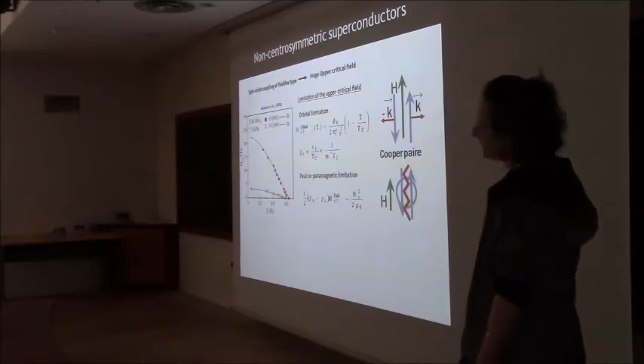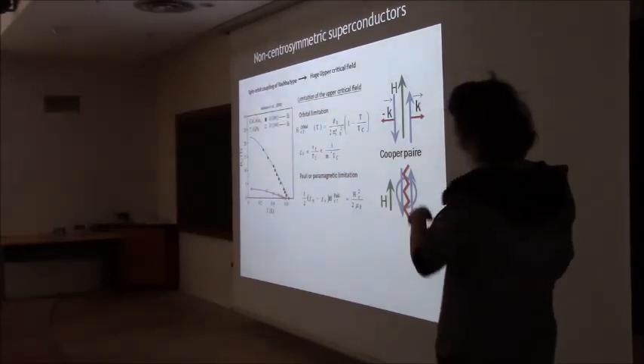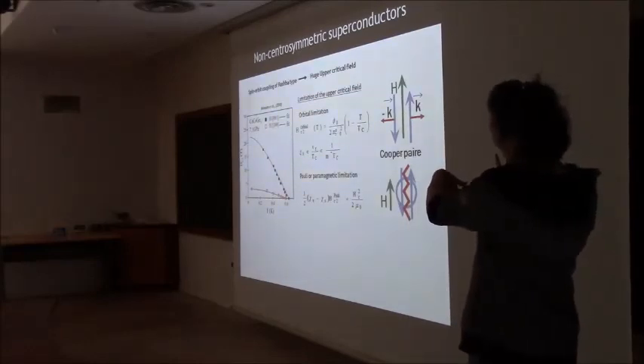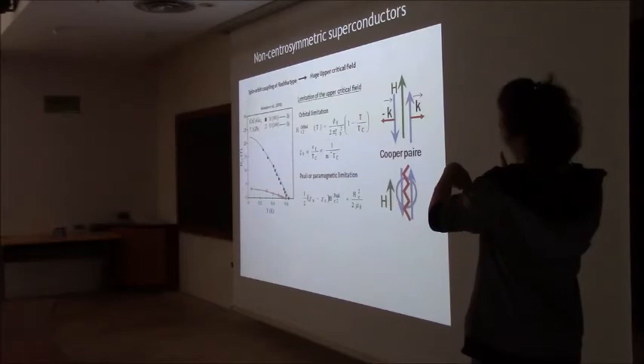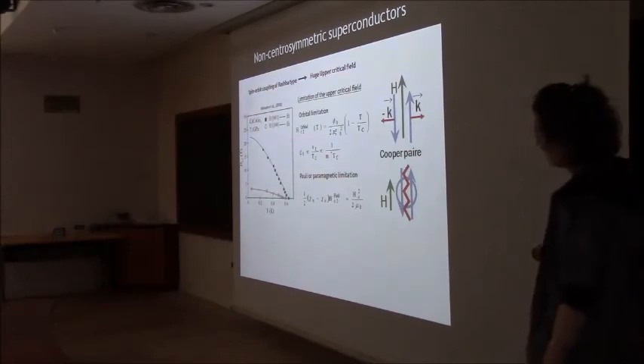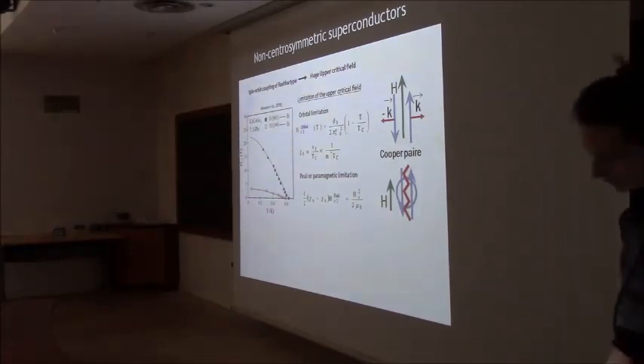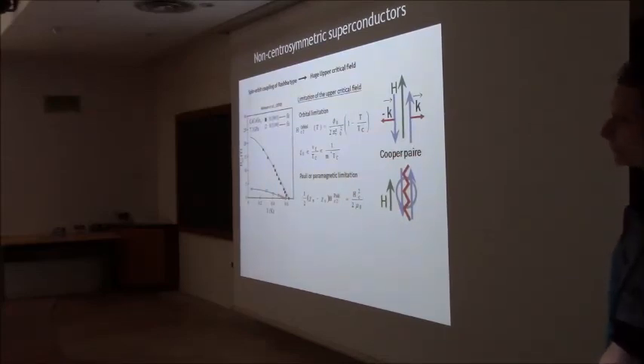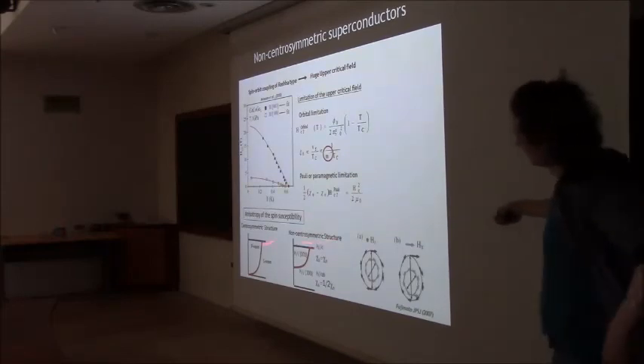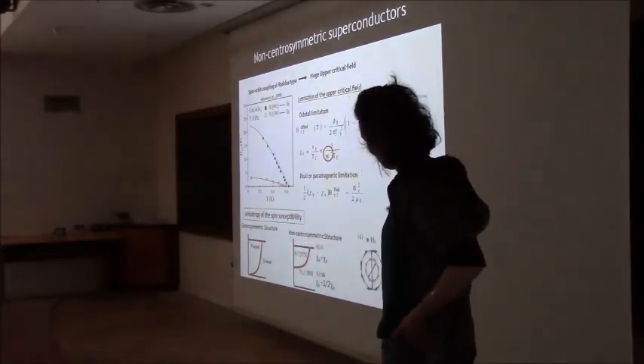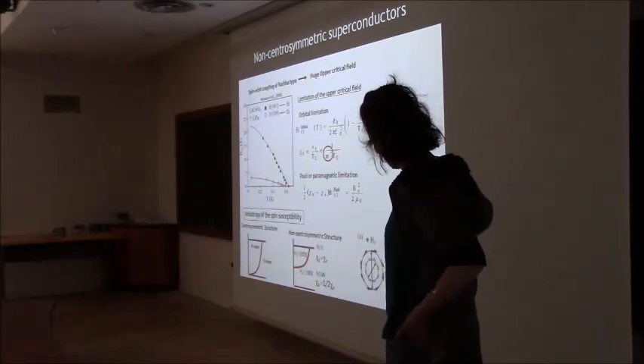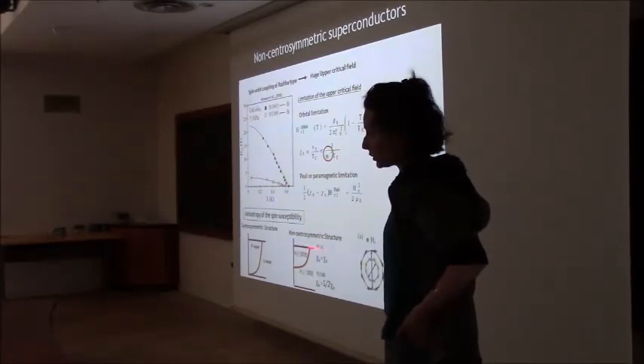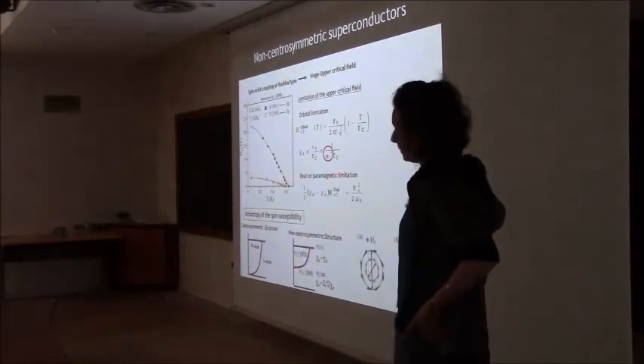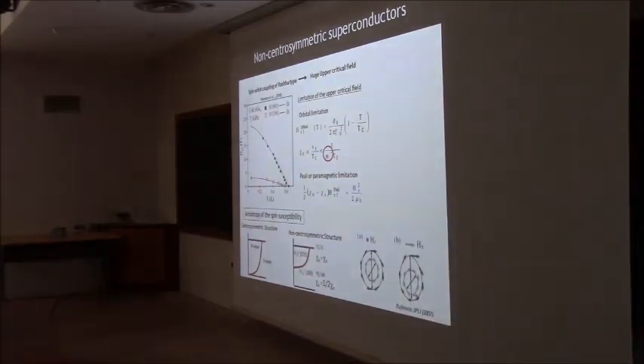And you also have a Pauli limitation. The Pauli limitation is that you have a Cooper pair, and because you have a spin flip, you have a tendency to align the spin along H, and you break the Cooper pair. This limitation will not apply for this compound, because if you apply a magnetic field along the gradient of V, then the susceptibility is constant when you cross the transition. So this does not hold. You don't have a Pauli limitation.